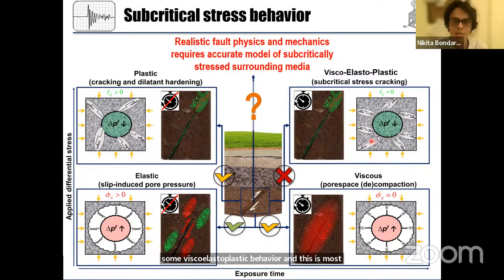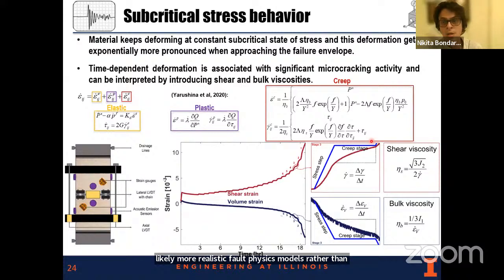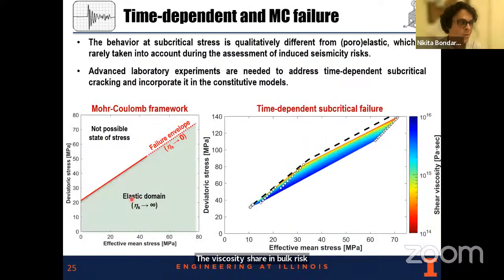To highlight our research in this area, we performed subcritical stress failure tests, where we step by step bring the material closer to failure, and then expose it to a constant state of stress over a prolonged time period to calculate parameters associated with the time-dependent response, the shear and bulk viscosity.